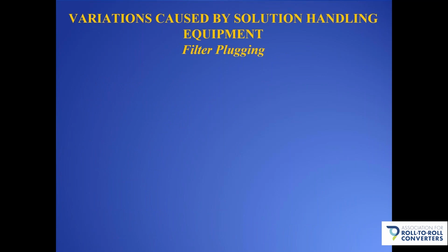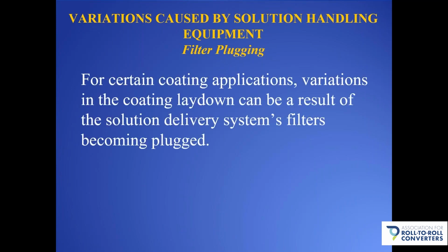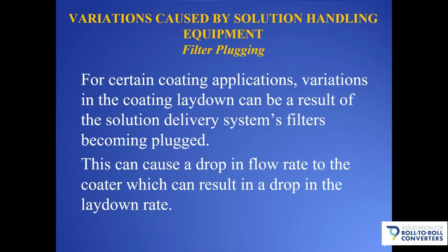Another issue is filter plugging. For certain coating applications, variations in the coating laydown can be a result of these delivery systems' filters becoming plugged. And this can cause a drop in the flow rate to the coater, which will obviously result in a drop in the laydown rate.